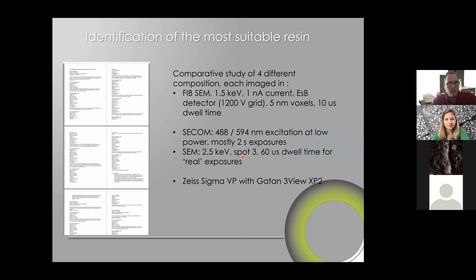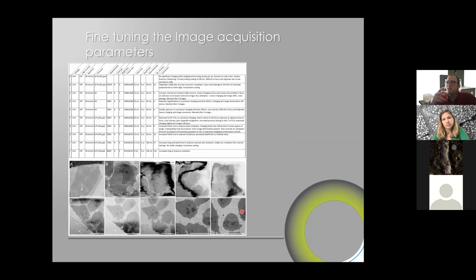It was definitely not something I would say mathematic driven or physics driven. It was a feeling from biologists doing some work. And they did the test for each of these resin, both with the FIB-SEM, on the CLEM, and on the 3View Zeiss Sigma. So basically, each block was tested these 3 times, and I already had the TEM images before. And they identified that one of the blocks was behaving better, and then they figured by successive steps what were the best imaging parameters. And this is where we started to have something like a hint. We had a product we could start to try to diffuse.